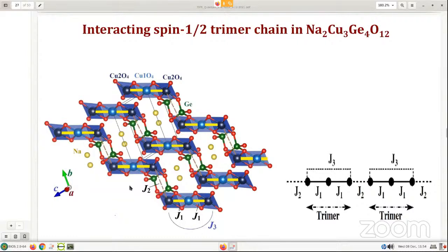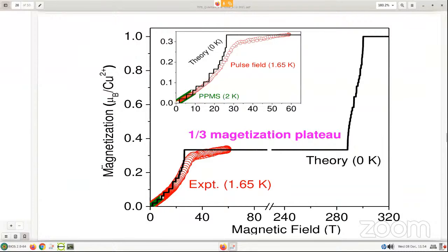Now the question is whether 2 trimers interact. I will only show that this system shows magnetization as a function of field. There is a clear-cut one-third magnetization plateau, and you see at what field it occurs. This is in Tesla. This is the VSM or PPMS data. Then we had to do the high field experiment in Germany. And you see this one-third magnetization plateau, and the theoretical work which we have done with Manoranjan from SN Bose, and you see the beautiful representation of this one-third plateau, and of course there is a field-induced saturation. It occurs at nearly 300 Tesla.